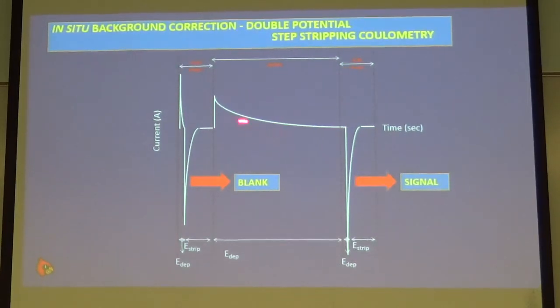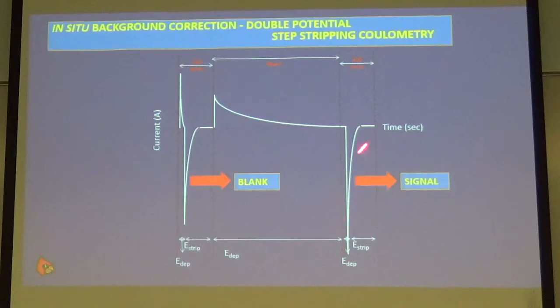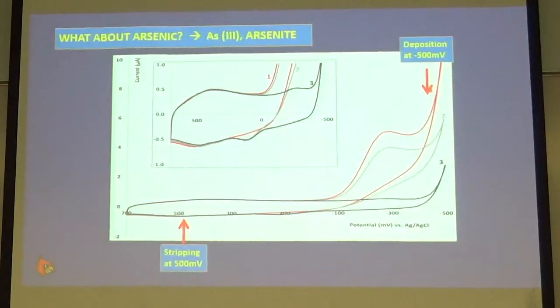Then we do a third pulse where we step out to the reducing potential, the deposition potential, again, but now we sit out there for a minute or two. So now we actually exhaust the cell and plate out all the copper or arsenic. Then we step back to do the stripping, and now the stripping signal contains the charge for the oxidation of the copper or arsenic. So it's the difference between this line and this line that really creates the current we're interested in. This is important because this simplifies the experiment out in the field. We don't have to do as much pumping as we might have thought. So let's get to arsenic.